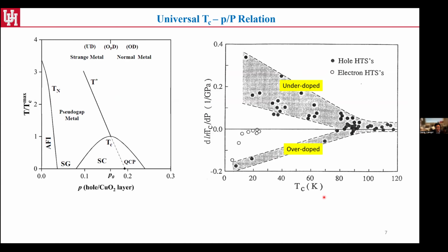Speaking of this universal TcP relation, I think we are all familiar with it. Basically, through doping, for most materials, Tc forms a dome shape. It's well mapped, a very nice story. But looking at it the other way, if we really trust these rules, it also means the maximum Tc is already well defined. That's why, normally, if we start to see Tc dropping, people searching for higher Tc may want to stop there to save effort, time and money. But the question is, is that really true? If you see the dome, is it really the case that nothing will happen beyond the dome, by doping or by high pressure?